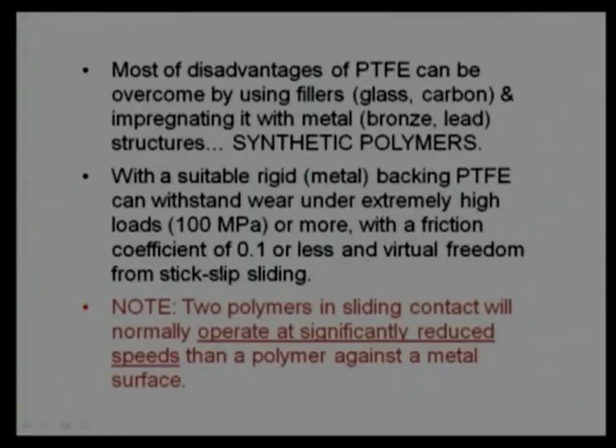In the case of PTFE, they show the same static coefficient of friction and almost the same kinetic coefficient of friction, there is no variation. That is why we say that it is almost free from stick slip phenomenon. That is why PTFE can be utilized. Of course, as I say, PTFE alone cannot be utilized, it needs to be mixed with some fillers and needs some support, so that thermal conductivity is increased and the ability to resist compressive force increases.